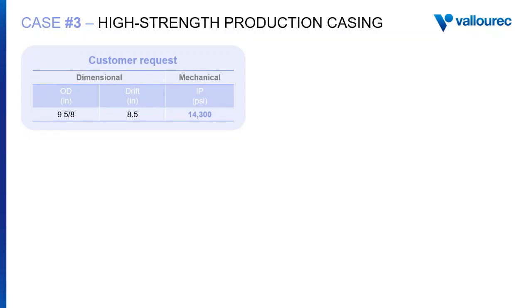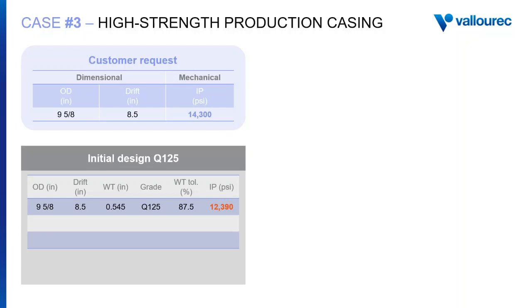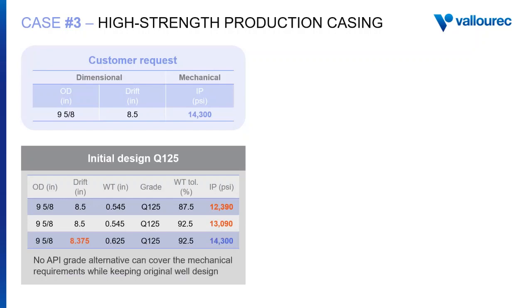To summarize the customer requirements, a maximum OD of 9 5/8 and a minimum drift of 8.5 inches were mandatory while achieving a minimum burst resistance of 14,300 psi. The customer's first choice was a Q125 grade with a minimum remaining body wall required by API of 87.5%. But the burst resistance was 12,390 psi, well below the minimum requirement. Even by increasing the remaining body wall up to 92.5%, the internal pressure resistance was not enough, leaving the operator only with the alternative to move to a thicker tubular and reduce the drift, which was not acceptable by the operator. In one word, the API grades were not able to offer a solution.